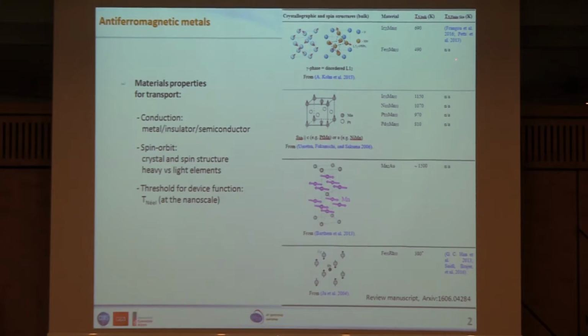Here we see that there is really a gap of knowledge as far as finite size effects on the Néel temperature are concerned. Why? It's because there is, to my knowledge, no versatile technique to measure this quantity, and I will show a technique to measure finite size effects on the Néel temperature. Finite size effect in itself doesn't mean much, it all depends on the bulk Néel temperature. For iridium manganese or iron manganese, finite sizes start at 5 to 8 nanometers. So below 5 to 8 nanometers, there will be some finite size effects.